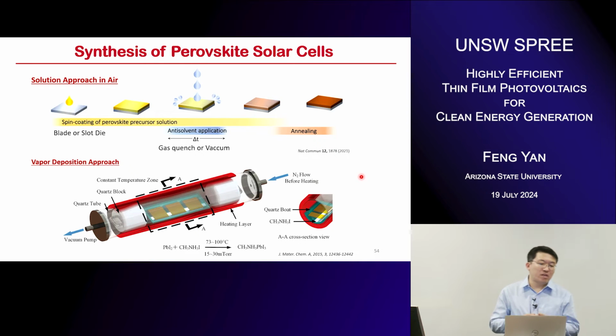Traditionally, they have two major ways to grow this perovskite. For the solution process, including the spin coating, the blade coating, slot die coating, to be honest, I'm not an expert in this area. So we initiated a new project trying to use physical vapor deposition, but it's pretty challenging because it's difficult to control. Compared to the cadmium telluride, which melts above 1000 degrees, right? The antimony selenide can melt around 600. But this one only melts at 100 or 200. So it doesn't mean the lower the better, but the lower, the more challenging to control it. So that's why this material majorly still uses the solution process.